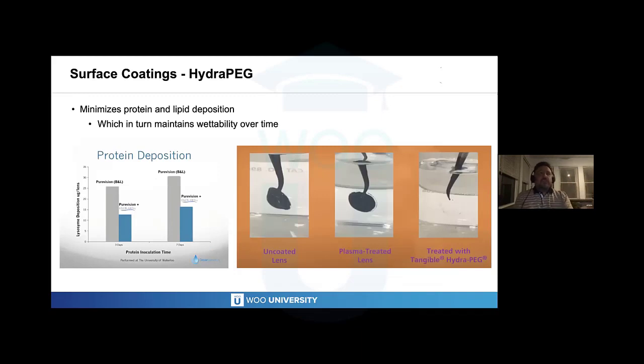We talked about the fact that when you keep a lens surface wetted and coated with something that has a better wettability, you're going to see less surface deposits. And you can see again, this is an example using just a soft lens material, but again, a significant 50% or more reduction in protein deposition.